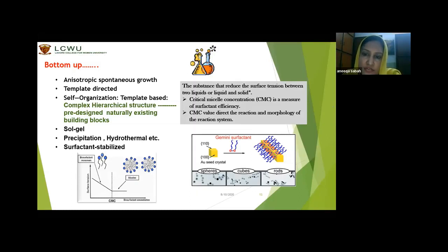Their concentration matters to measure the efficiency of these salts or these materials. The polymers are also used as a surfactant. They are actually used to stabilize the size of our prepared nanoparticles. They can also act as a reducing agent. So the critical micelle concentration value directs the reaction and morphology of the reaction system, and we can get structures like spheres, cubes, and rods.